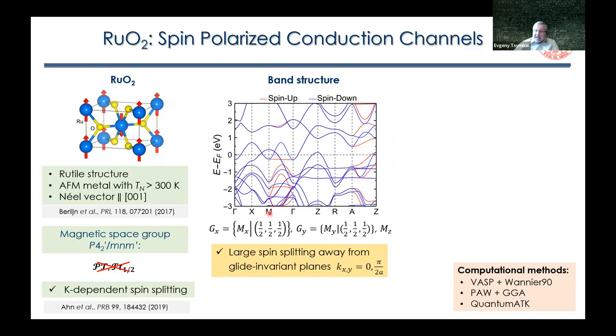And as you can see, along certain lines, we don't have spin splittings. These are lines which are sitting on glide invariant planes, where kx and ky are equal to π/2a. And this is because on those planes and on those lines, the glide symmetries hold. As a result of the presence of these glide symmetries, the bands by symmetry must be spin degenerate.